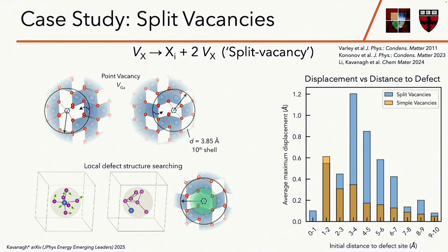And that's because it is somewhat unique, and it is what we would call a non-local reconstruction. So unlike typical defect reconstructions or rearrangements that would usually involve some movement of the neighboring atoms around the defect site, or first nearest neighbor shell or the second nearest neighbors, this actually involves the movement of an atom much further away from the defect site, moving closer to the defect.